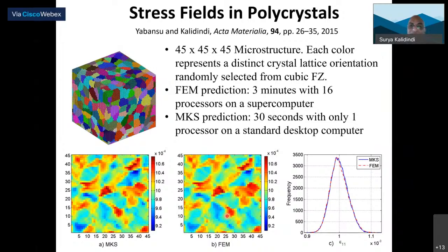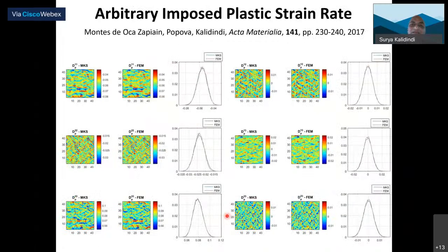This is elasticity. You can do the same in plasticity. In plasticity, you worry about the plastic strain rate tensor. And these are the 6 components of the plastic strain rate tensor. So we can actually do every component in every voxel for any microstructure of that material system. And we are now beginning to say any material system, but we are still working on that.